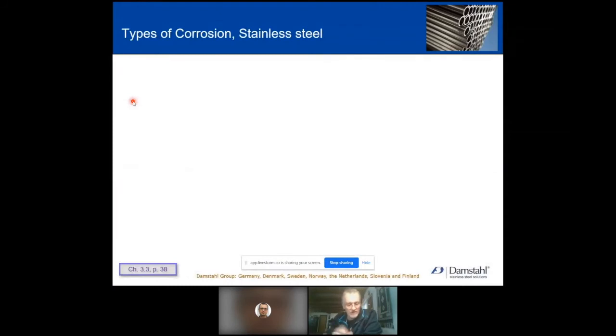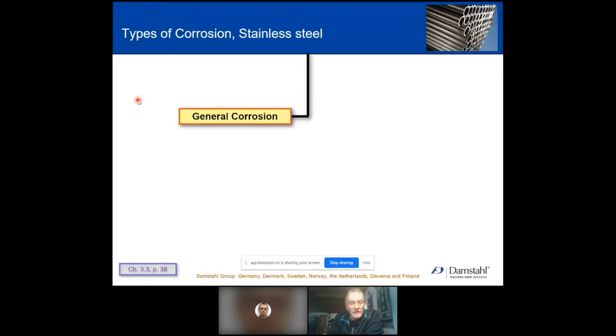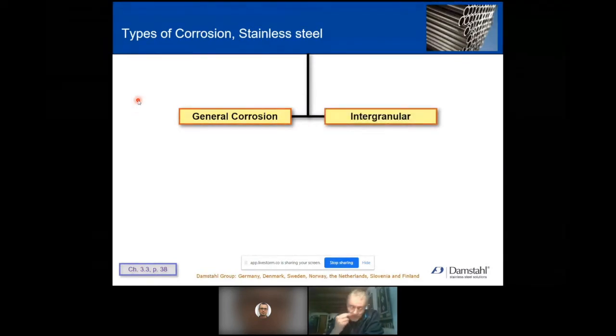Depending on the state of this oxide layer, we actually get 5 different types of corrosion. General corrosion is superfluous within food pharma, because it only takes place in very strong acids, usually strong sulfuric acids, sometimes very strong bases as well, but mostly it's a sulfuric acid problem. Intergranular corrosion occurs if you have too much carbon in the steel. Then you get some weakening along the grain boundaries, and you get selective attacks along them. But these days, the mills are very good at keeping the carbon low, usually below 0.03%. So intergranular corrosion is a kind of antique type of corrosion which doesn't really exist anymore.